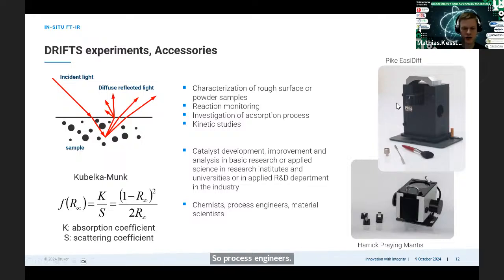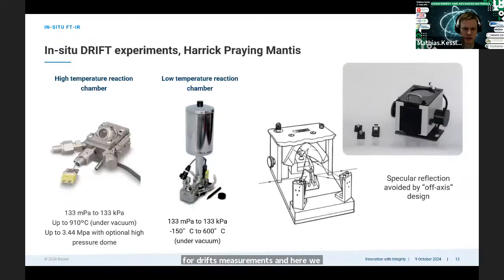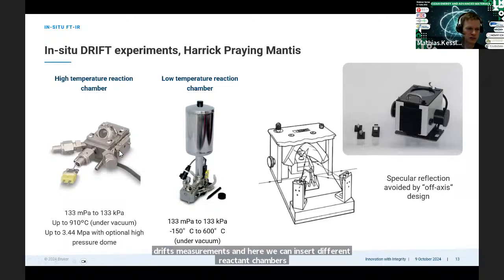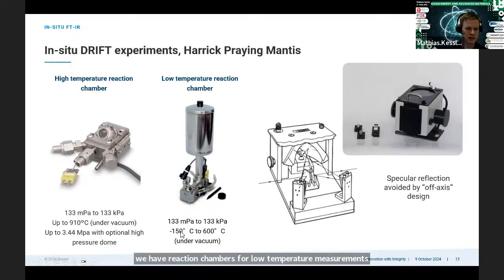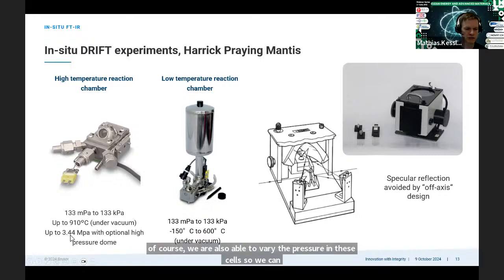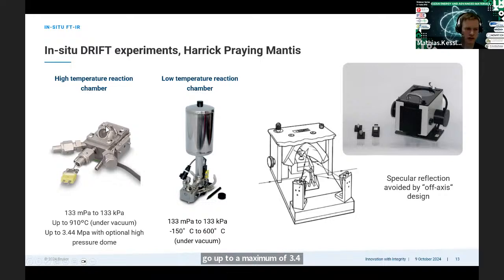On the right, you see accessories which are available for fast DRIFTS measurement. This is the EasiDiff. So this is for studies at standard environmental conditions, so room temperature, standard pressure in the atmosphere. And then we have the Harrick Praying Mantis reflection accessory for DRIFTS measurements. And here we can insert different reaction chambers. So we have reaction chambers for low temperature measurements, shown here in the center, where you can cool down to minus 150 degrees. And we have a high temperature reaction chamber, which can be used up to 910 degrees centigrade. And of course, we are also able to vary the pressure in these cells, so we can go up to a maximum of 3.4 megapascal with a high pressure dome attached to this cell.